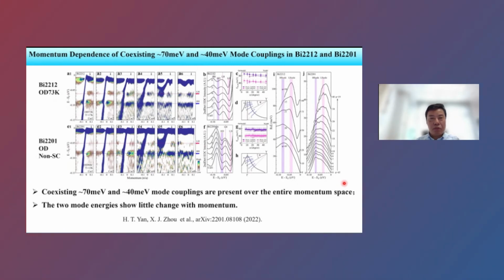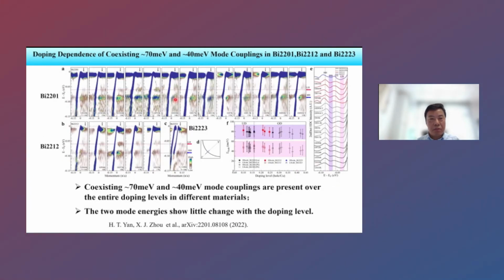Also, we measure many other materials, many Bi2201 samples with different doping from heavily underdoped to heavily overdoped, non-superconducting. A lot of samples with different doping levels. You can really see that the two modes, 40 meV and 70 meV, are all there. It doesn't change much with the doping. Also Bi2212, the same thing, from underdoped to overdoped. We can even see that these two modes also exist in Bi2223 samples. So they are really different materials.